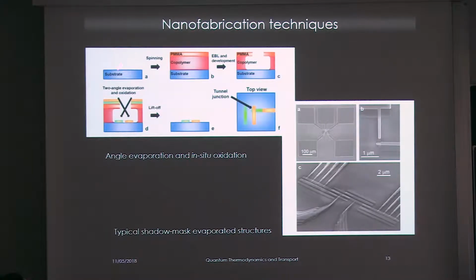All these systems are typically made on substrates of silicon oxide or sapphire. We use a suspended mask made of polymethyl methacrylate, PMMA, and then with electron beam lithography, one designs a suitable structure. We use several angle evaporations to make shifts in the structures, and then oxidation, and then one is able to perform complicated and exotic structures exploiting different materials, from normal metals to superconductors and so on. All the structures that I will show you are realized using this kind of technique.